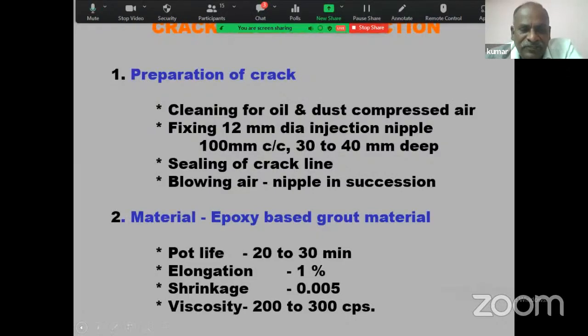Preparation of cracks. Surface preparation is over. Then after that, you have to go for the crack preparation. All the cracks are to be properly prepared, with oil cleaned and dust removed by compressed air. So this is what we have to do.